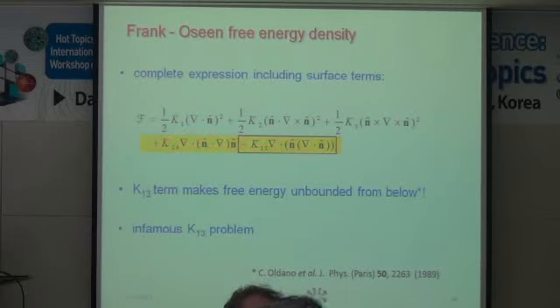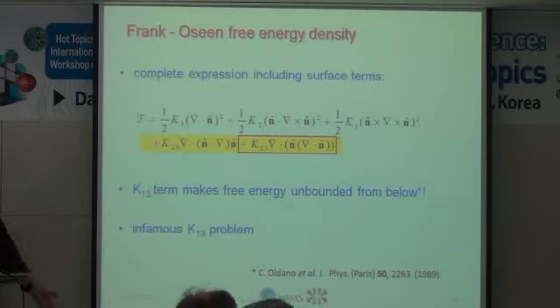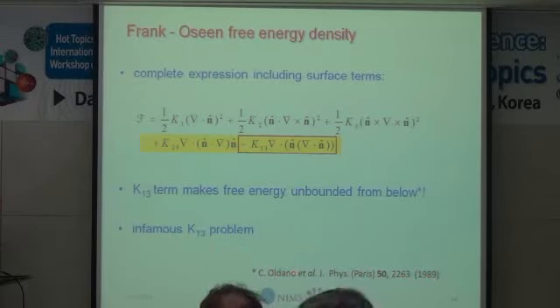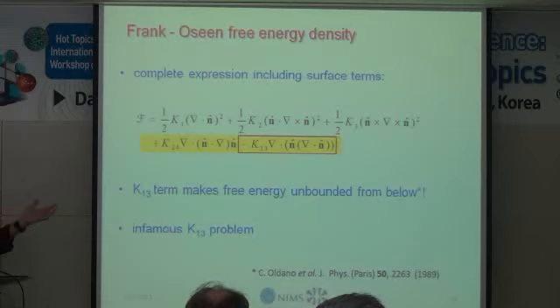And it turns out that this one here is really a problem, because this term makes the free energy unbounded from below. That is to say, if you include this term, you can make the free energy as negative as you like. And that's obviously a major problem. So this wasn't noticed early on. Saupe, again, introduced this, but it was only in '89 that Oldano identified this problem, and it's called the K13 problem. And many papers have been written on this, and there have been almost religious wars on this topic. But it still stands somewhat unresolved today. So I think it's kind of a fascinating problem.